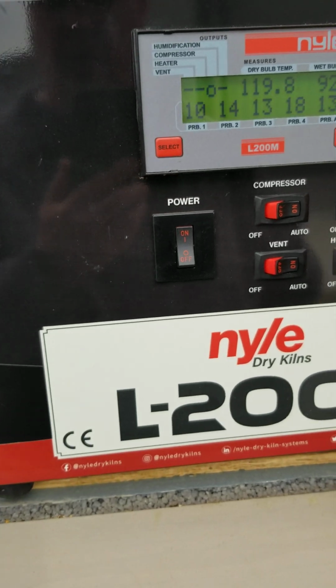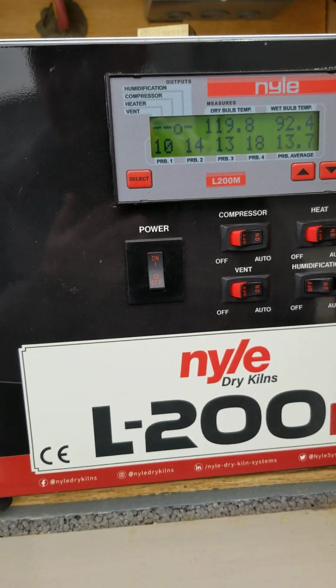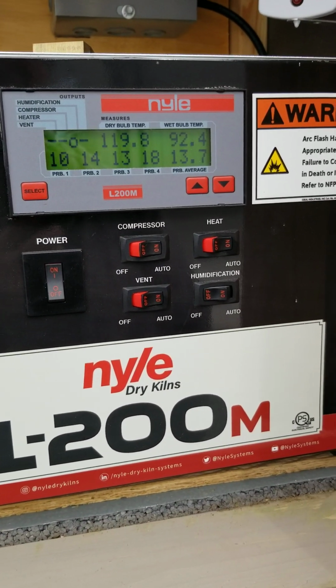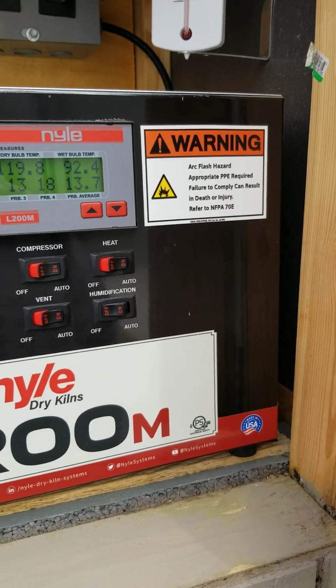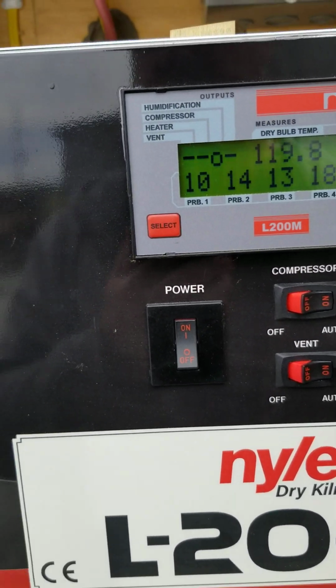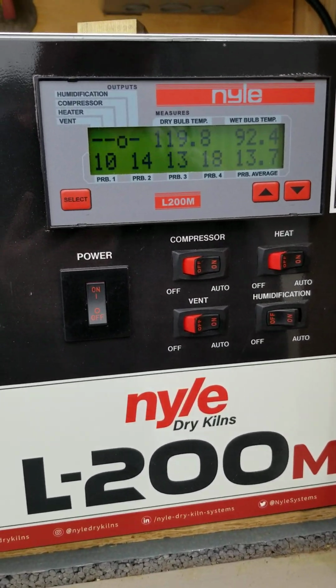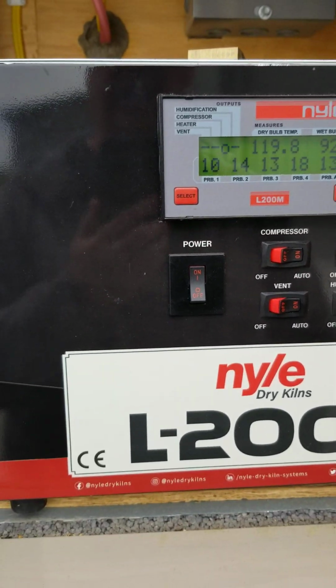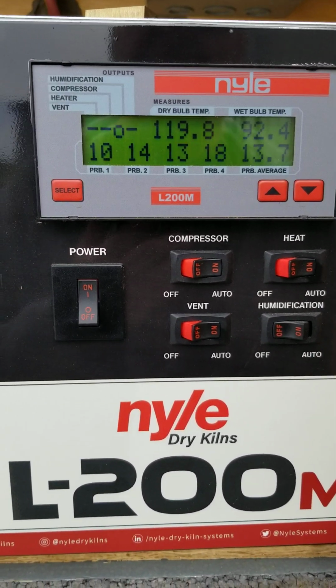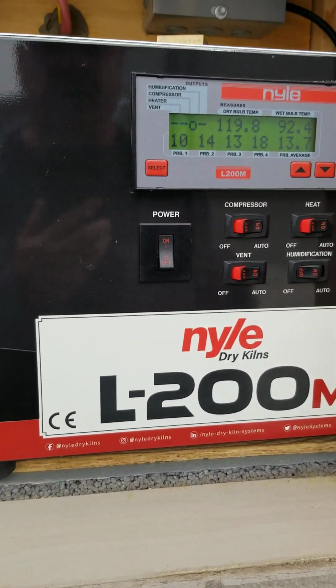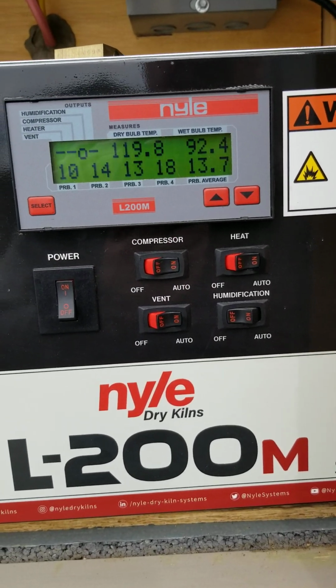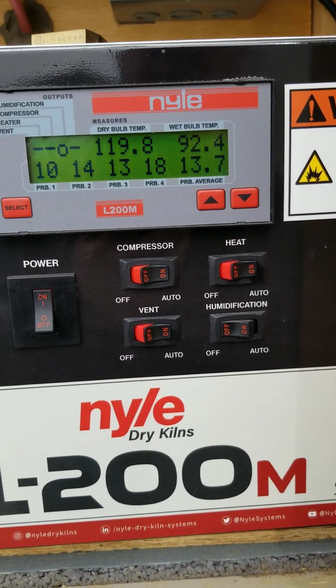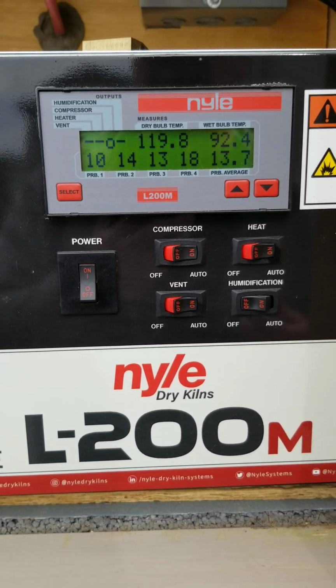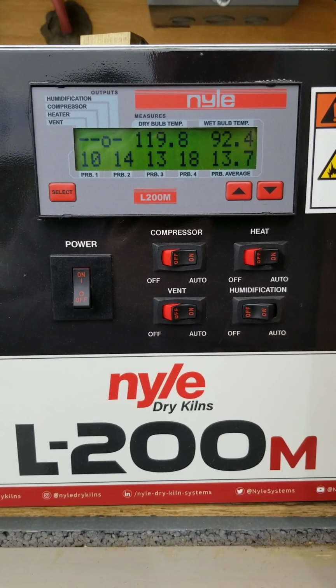I think one load last year I did a load of 8/4 that I rushed a little too much. It didn't have enough time to dry outside. I put it in the kiln. The kiln moisture came down pretty good, and I think we had it come down too quick. It should have been longer air drying, or I should have slowed the kiln down and dried it at a slower pace.